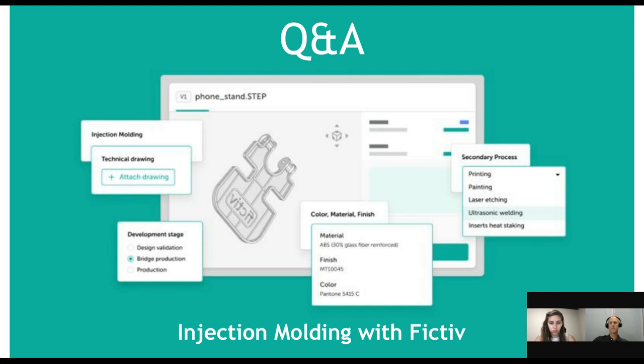The reason is the surface that's actually touching the tool. So you have some variance there. With a high polish, more of the part's surface is in contact with the tool, which creates more of a struggle to eject the part. So usually within the B3 to C3 range would be better for no draft parts. Obviously, without draft you still have some cosmetic imperfections, so you may have some drag marks, but as long as this is understood and acceptable, it can be done.